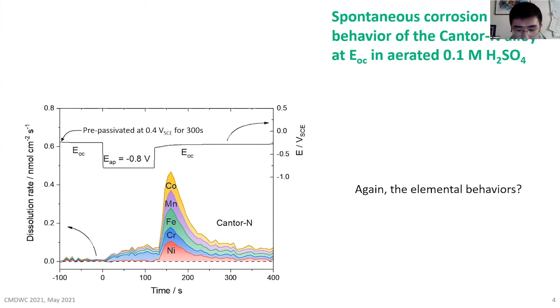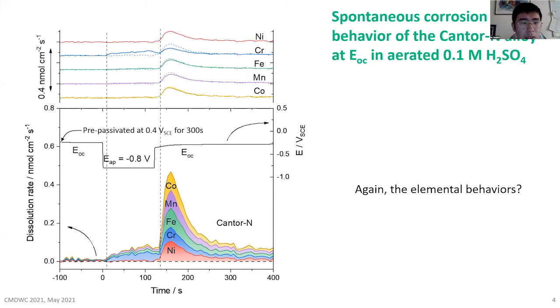With the help of AESEC, we can detect the individual contribution of each element. We did the same calculation for the congruent dissolution, and we observed the same results in the cathodic activation step. There was excess chromium dissolution, and it indicates the passive film dissolution. And during the second open circuit potential, we observed that the real dissolution rate of the chromium was much lower than the congruent dissolution rate. So it implies that chromium enriched at the surface during this step. So we attribute it to the spontaneous passivation of this alloy.